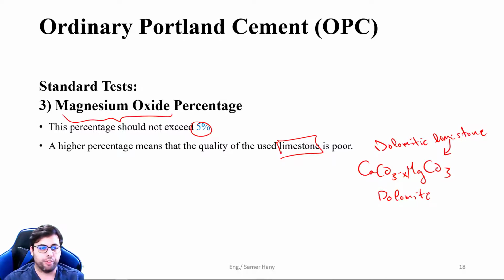So if we calculate our loads and we need like 100 kilograms of cement for a particular application, this means maybe 5 to 10 kilograms of that cement will not actually contribute to the strength and the coherence of the building unit we're building, and we're underestimating the cement that we're using. Okay, and it will fail at a lower load consequently.